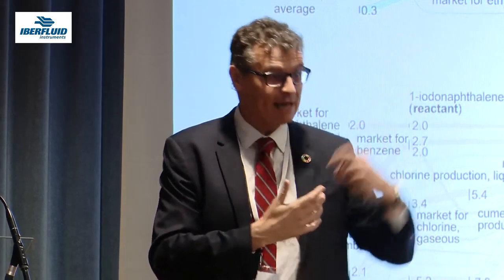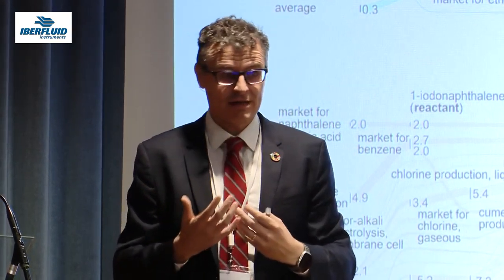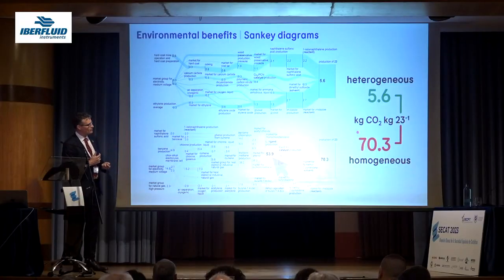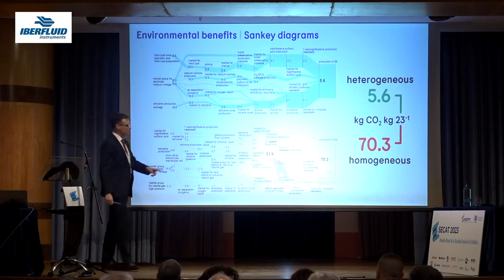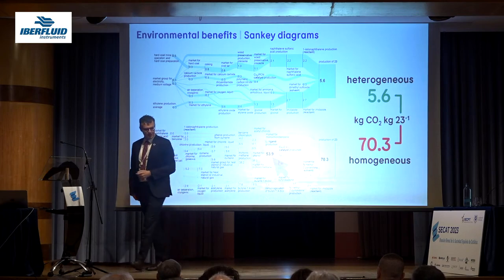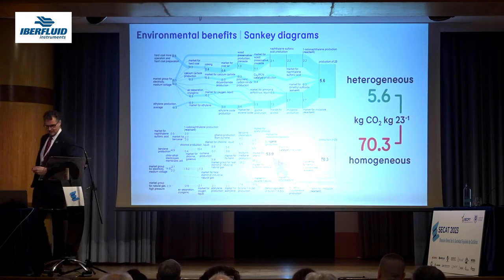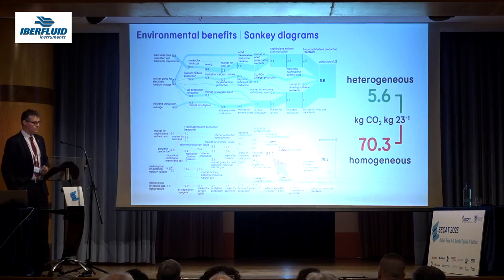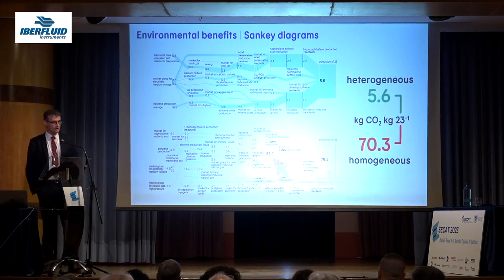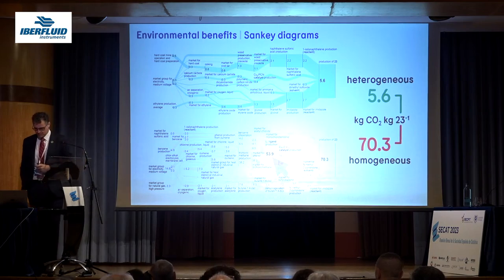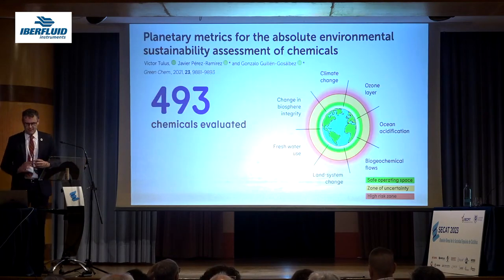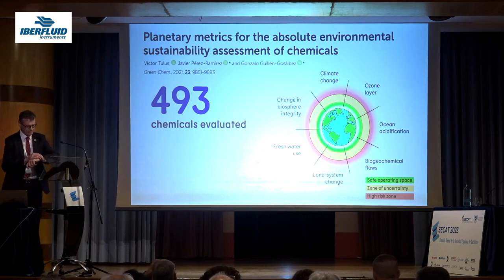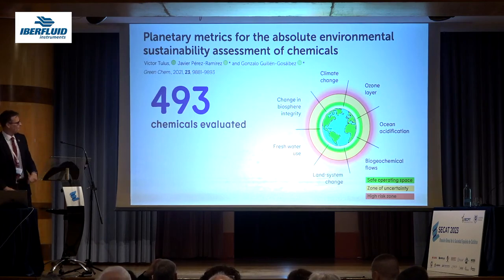Is it the solvent? Is it the ligand? Is it one of the reactants? Is it one of the purifications? Is it one of the separations? What is it? And what you can see is that the advantage of one order of magnitude lower footprint is, in this particular case, due to the large footprint. So out of the 70.3, 50.9 of the carbon footprint is due to the synthesis of the ligand that you need to do the homogeneously catalyzed reaction. The very final part, I will take only 5 minutes, if I'm allowed.